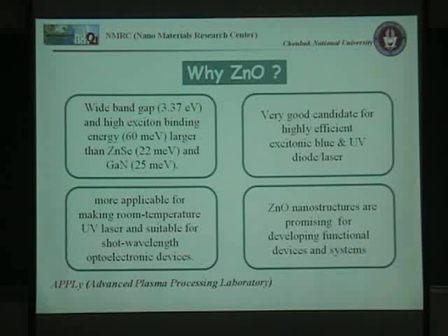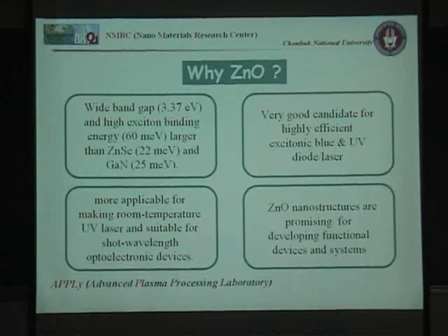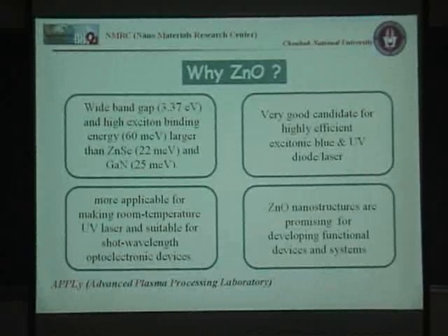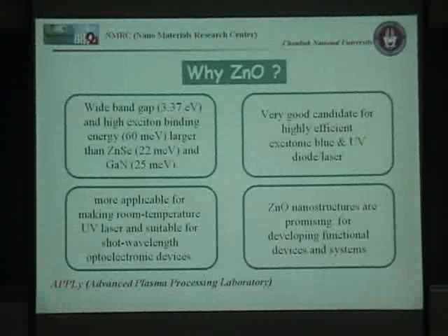Its exciton binding energy is about 60 milli-electron volts, which is larger than other semiconductor materials like zinc selenide and gallium nitride, which are about 22 and 25 milli-electron volts. It is well known that the exciton binding energy must be larger than the thermal energy at room temperature to show efficient laser emission at room temperature.